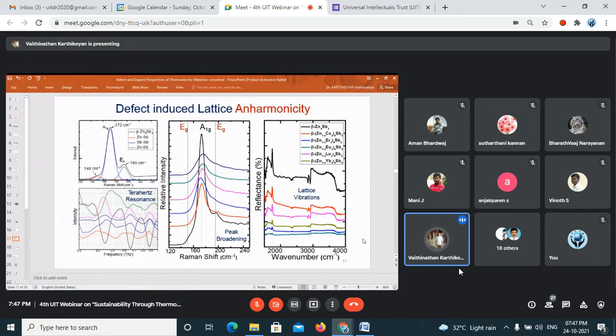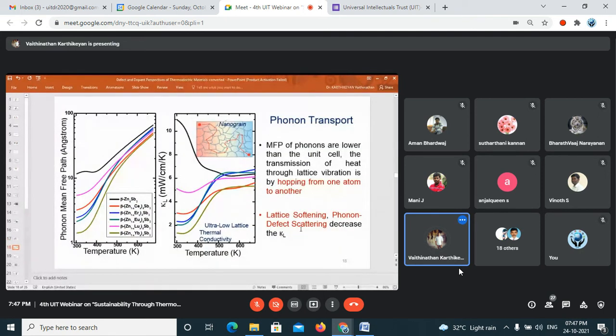This demonstrates a decrease in values of vibration, because the vibrations are being nullified by the defects of the material. Then this is the phonon mean free path observation. You see the black curve has a higher mean free path of phonons, which means the phonons can travel a longer distance in the undoped material. After doping, you can see that it drops drastically, which means the phonons are being arrested and not allowed to travel a longer distance, so the heat cannot travel a longer distance.